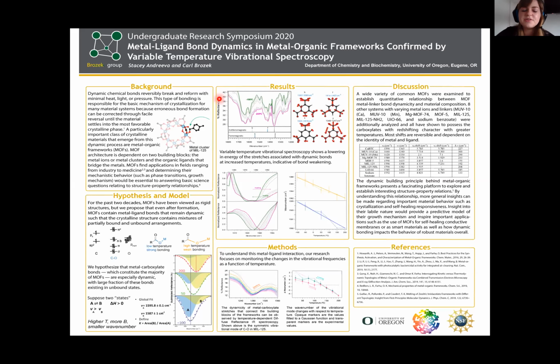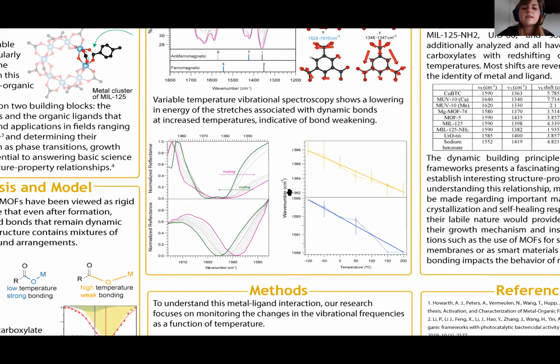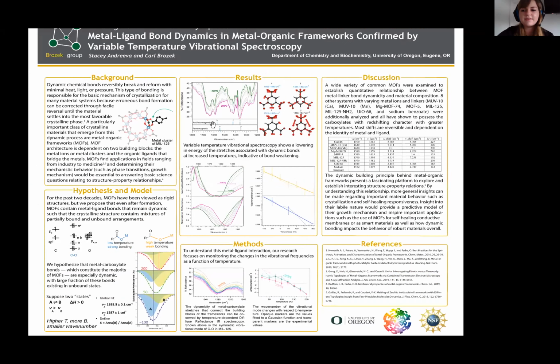So our representative system was copper BTC, and we showed that at lower temperature, we observed the asymmetric carboxylate here, and with higher temperature, it shifts to lower in energy, almost by 6 wave numbers, if we can zoom in here. This could be an important work to show how we could tune properties of metal organic frameworks and achieve control of structure property relationships. Right. I'll end it here.